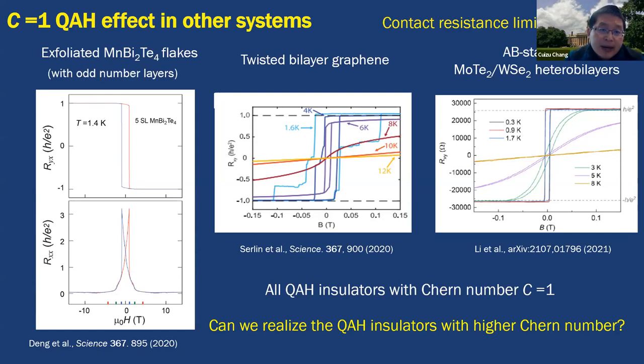I can tell you that in magnetically doped topological insulator films, if we use the ratio Ryx over Rxx equal to one as a criterion, the critical temperature should be around 10 Kelvin. We can see the quantum anomalous Hall state starts to appear at 10 Kelvin. But if you want very good quantization, it should be in the milli-Kelvin regime. That's also the reason why in our measurements we usually perform dilution measurements. We want to get 99% quantization. But here in manganese bismuth telluride, although the temperature is 1.4 Kelvin, the quantization should be less than 97%.